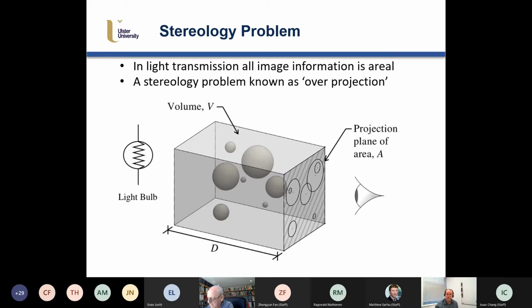That causes what we call a stereology problem. It was backlit and observed from the front. This is a solid model that I developed here, and you can see that individually, none of these particles are impinging with each other. They're all isolated, separate, individual particles. But when you project them onto the front, you get this problem of overprojection. Some of them seem to be overlapping, but they're not. And some of them will be unobservable because they're either obstructed from view or in the shadow of a bigger crystal. So you don't really get a true representation on the plane. You get an areal representation of what happens in 3D.